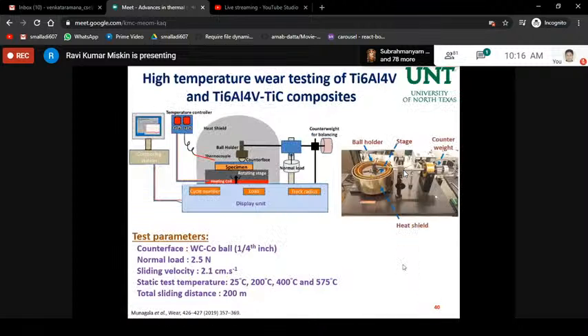Next. So we did some high temperature tribology, and I won't go into too much detail, so I'll just present an overview of what we did. This study was carried out in collaboration with University of North Texas. This is actually a high temperature study, where we expose our coatings to extremely high temperature, around 600 degrees centigrade, and we do the wear test at that particular temperature.